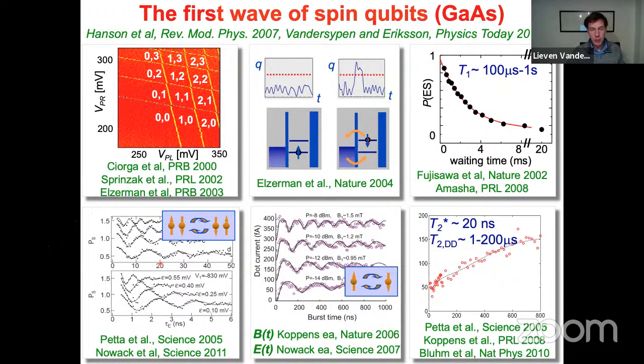So in both cases, it was possible to measure the spin dephasing and coherence time, and these timescales actually were very short, many orders of magnitude shorter than the T1. This is now about the timescale on which you lose track of the phase of the qubit. So it's not the population difference between the excited and the ground state, it's really the quantum mechanical phase between them. And so that dephasing occurs without any special measures. It occurs on a timescale of tens of nanoseconds. And the main origin for this is that in this gallium arsenide substrate, every gallium and arsenic atom itself has a spin attached to its nucleus.